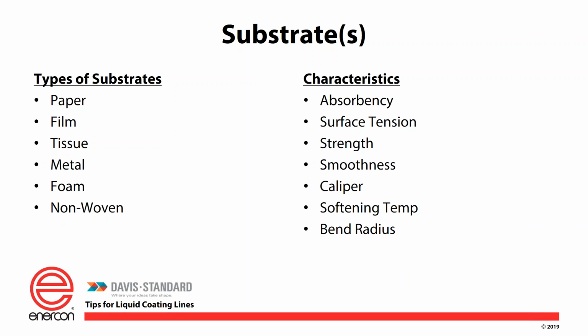Smoothness. Some products require a very smooth finish, whereas I'm going to run a paper on here and we want to put the adhesive on, but adhesive is a little more expensive, so we don't want to put as much on. You might put a third coating on here. Instead of your release liner first, putting your silicone on, maybe you put in a filler with a scrape coater, so we fill in all the valleys, maybe with a clay style coating. Make it very smooth and then put your release liner on it so that your adhesive is much less required to fill in those voids and make it stick. Also, what is the smoothness of the substrate when we're done with the product? That determines what type of coaters we're going to be applying it with.